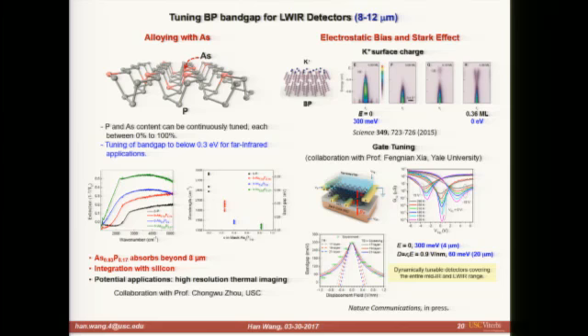As we increase this electric field, we see the effective transport band gap go down from 300 milli-eV, that's 0.3 eV, to 80 milli-eV. That corresponds to 4 micron wavelengths all the way to 20 micron wavelengths. So with just one material, you can cover both the 3 to 5 micron wavelength range and the 8 to 12 micron wavelength range.